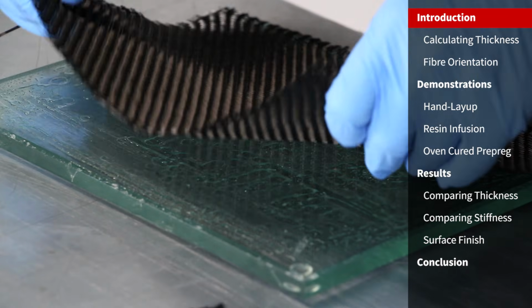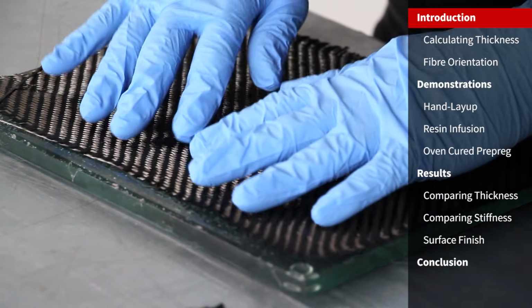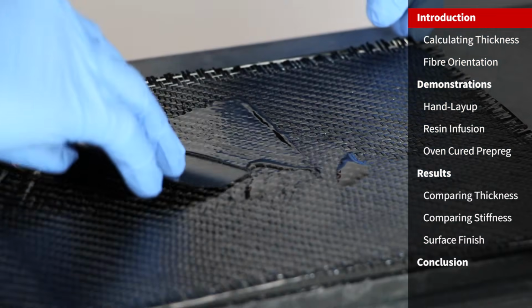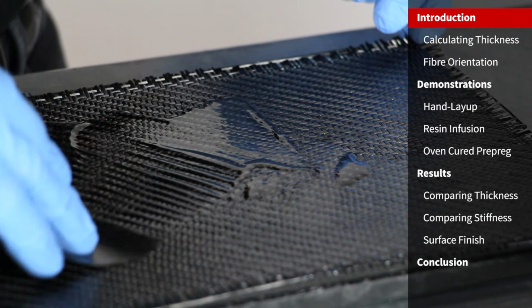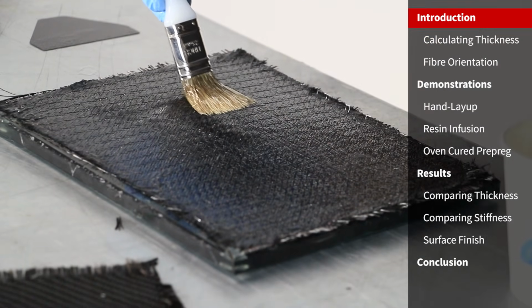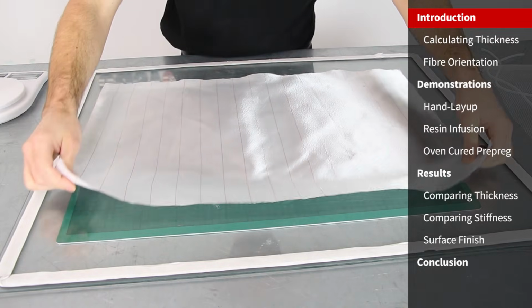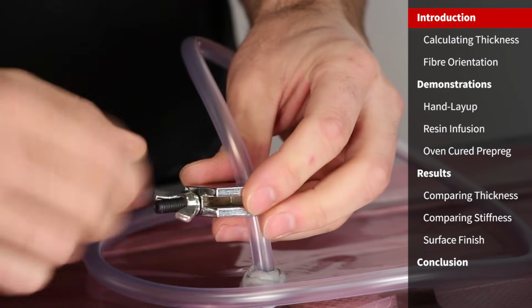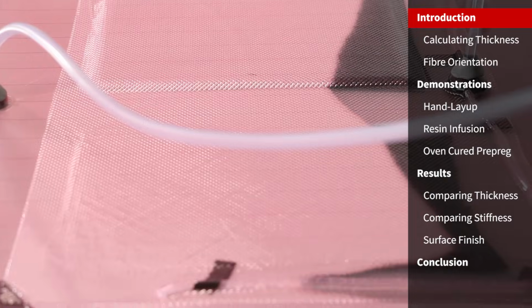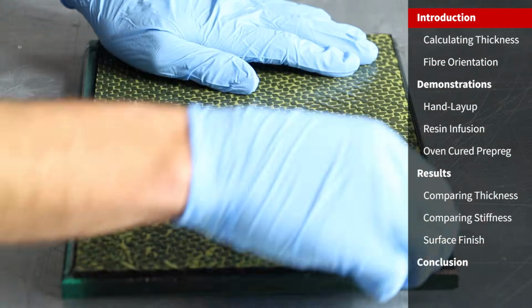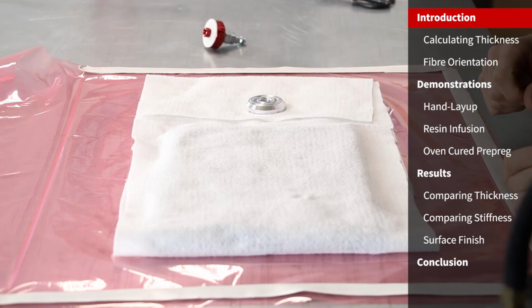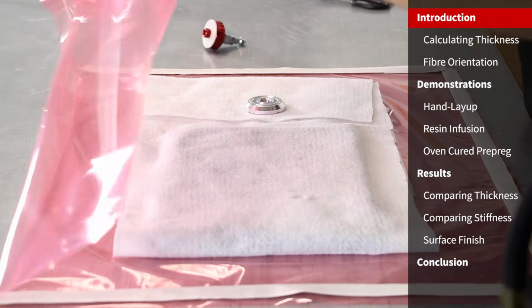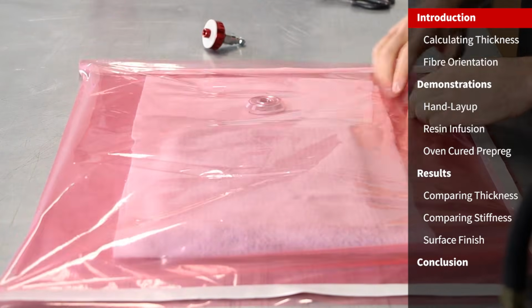your job. The three different manufacturing methods we'll be looking at today to make our sheets are a simple hand layup process using dry carbon fibre fabric hand laminated using epoxy resin; infusion, where we'll be using a vacuum process to infuse epoxy resin through a dry carbon fibre reinforcement; and finally oven cured prepreg, where we'll use uncured prepreg carbon fibre, vacuum bagged and cured under vacuum in an oven.